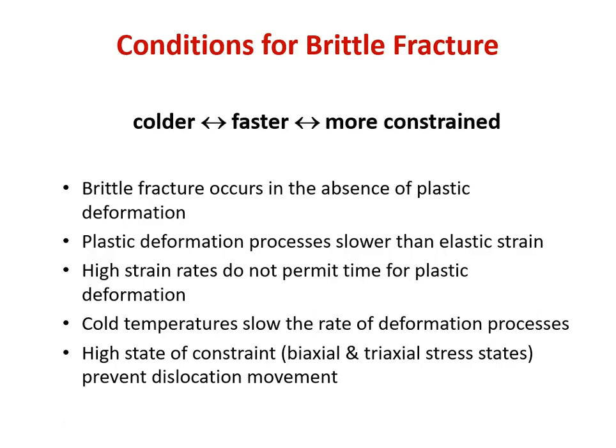And this is one of the reasons why thin coatings will act much more ductilely than a monolithic thick part. And it's why we can use brittle ceramics in thin coatings much easier than we can in thick sections. And I think we might have discussed that with material selection and why we would use a ceramic coating as opposed to a thick ceramic part for a pump housing. In any case, if we want to make something ductile, we keep it warm, we load it slowly, and we make sure that it's only loaded in one direction at a time. It's not constrained. Go with uniaxial rather than multi-axis stress.